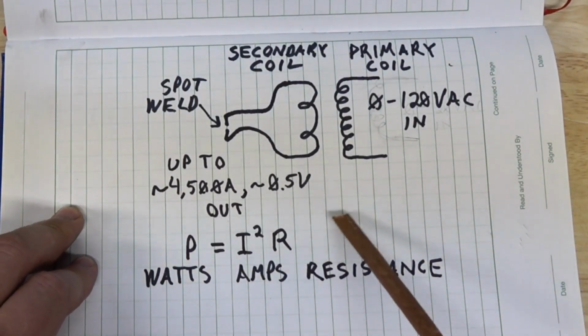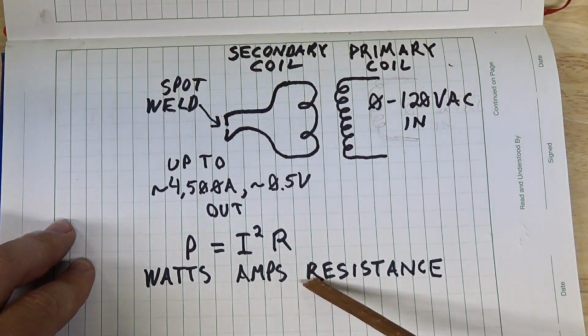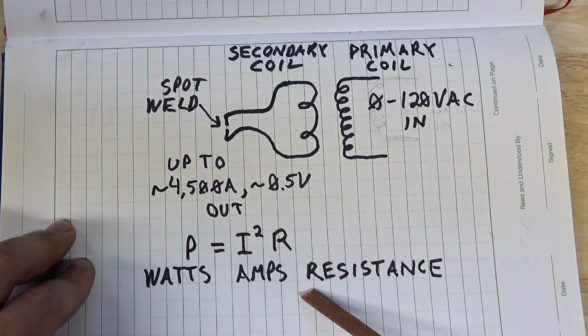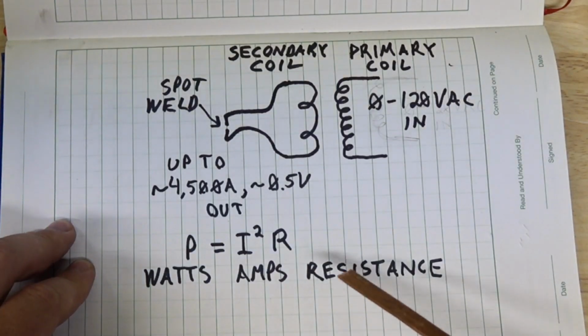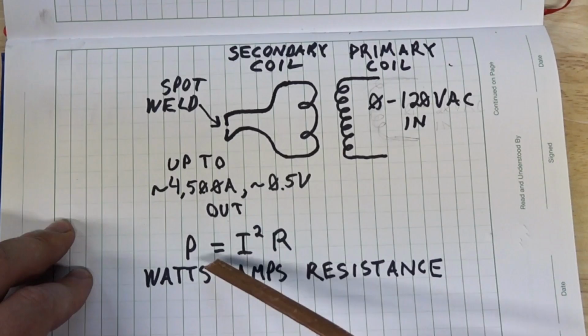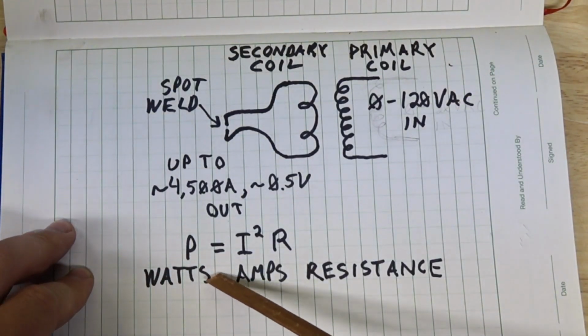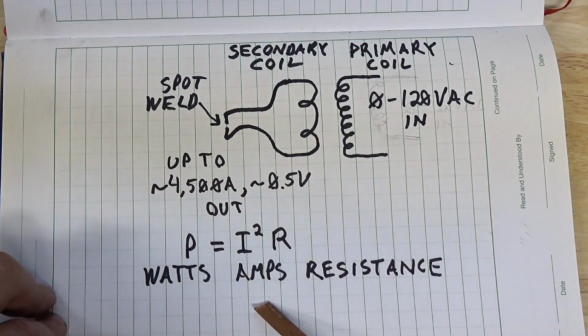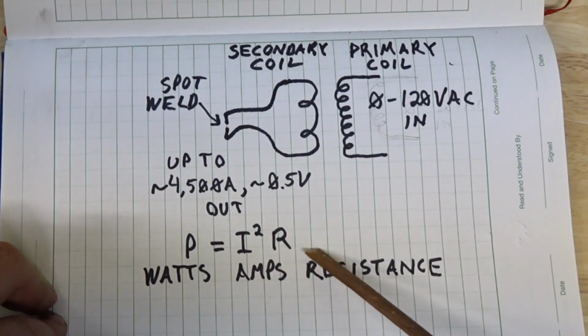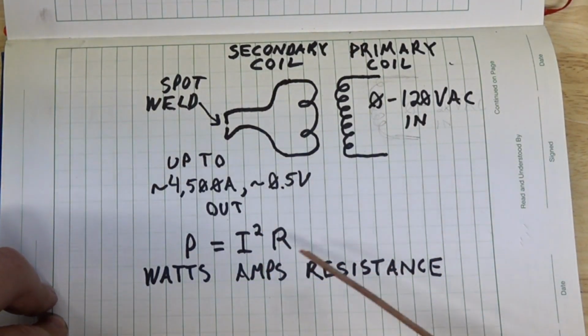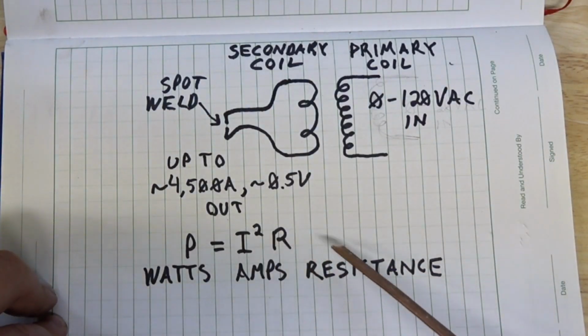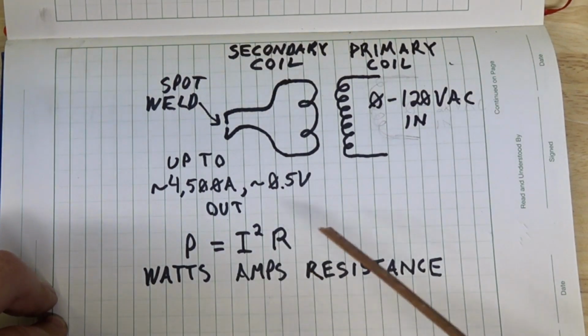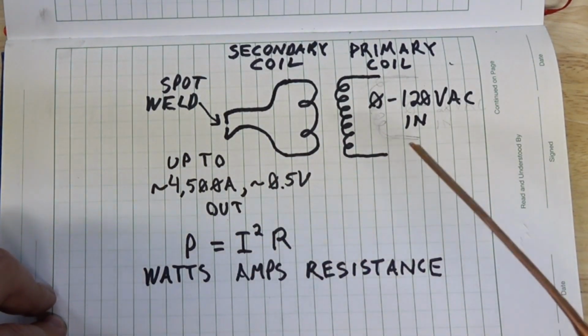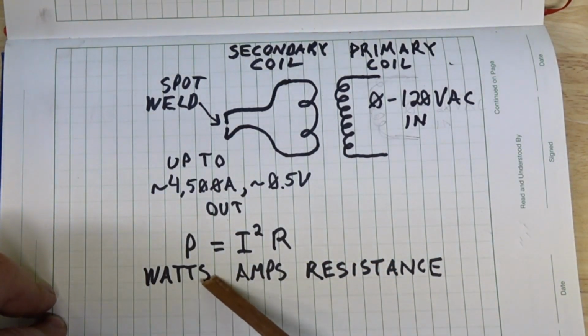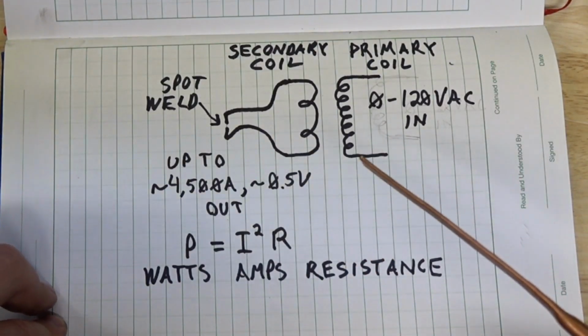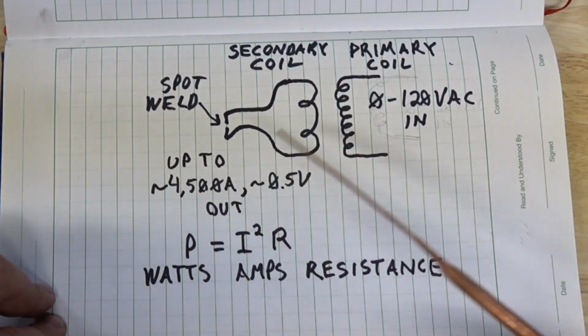It has downsides to it because you need something that isn't too conductive, because if you don't have a high enough resistance, you're not going to dump enough wattage, and so you can't really get the material to melt together well. Stuff like copper and aluminum is notoriously hard to spot weld, if not impossible. Usually if you're going to spot weld aluminum, you need a resistive layer of something like, let's say, nickel in between that will actually facilitate this resistive heating, because otherwise you just blow holes through the material essentially, or you overload your spot welder.